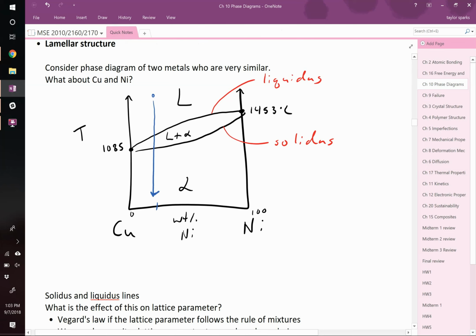What happens is that the second that it touches that liquidus line, right there, maybe that's at like 1100 or 1200 degrees Celsius, your very first solid starts to form. And the phase diagram tells you what the composition is of that solid. You would draw a flat line all the way over until it touches that point. You would drop a tie line down, and this we're going to write C_S. This is C naught. That C_S represents the composition of the solid that initially forms.